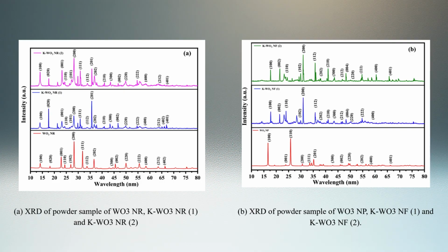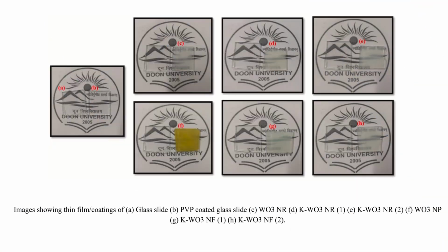The XRD patterns confirm that all synthesized materials are highly crystalline monoclinic WO3. Crucially, the data showed the potassium doping was successful, causing a slight shift in the characteristic WO3 peaks without introducing new impurity phases. This confirmed the incorporation of potassium ions into the WO3 crystal structure.